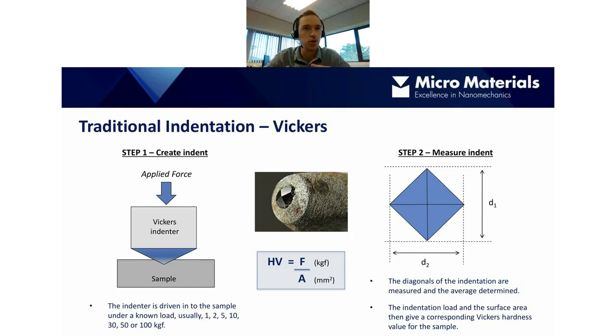So with Vickers indentation, as I'm sure you're all familiar, step one is we apply a force through a Vickers indenter, which you can see in the picture here. This is a four-sided pyramidal indenter. The force is applied through the indenter into a test specimen, and of course we get an indentation into the sample. The indenter is pushed into the sample with a known load, usually between 1 and 100 kilogram force. In terms of newtons, multiply by 9.8 to get the equivalent force, so it's roughly 10 to 1,000 newtons.